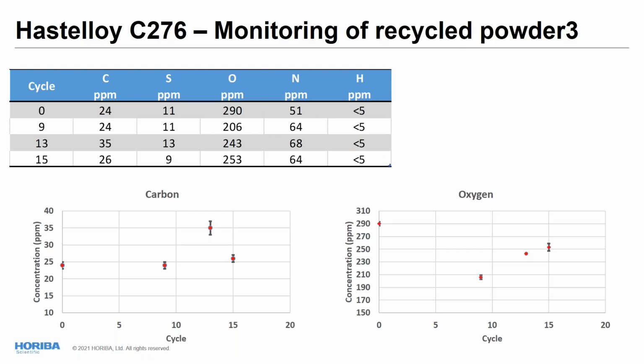But looking more closely at some elements, you can see for carbon here, there is a spike, and that is significant. And you can see we were jumping from 25 to 35 ppm. That is significant, but it was not confirmed on the cycle 15. And most likely this is due to the homogeneity of the powder and probably the sampling, since we are using only a few grams, less than 1 gram, to perform the analysis for carbon.